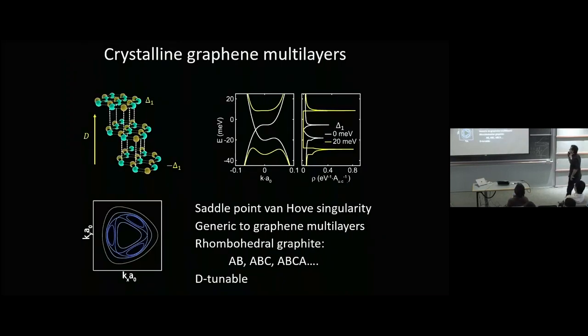Okay, so the systems that I'll talk about are mostly in the rhombohedral class of graphene multilayers. So this includes exotic metastable multilayers, ABC trilayer being the first one. These are not thermodynamically stable, but they are thermodynamically metastable. ABA Bernal stacking is the ground state of graphite structurally, but ABC is actually pretty stable. You can isolate these structures relatively easily just by exfoliation and finding them. But another one in this class is Bernal bilayer graphene, which is actually absolutely stable, and it's the conventional graphene bilayer that people have studied for many years.